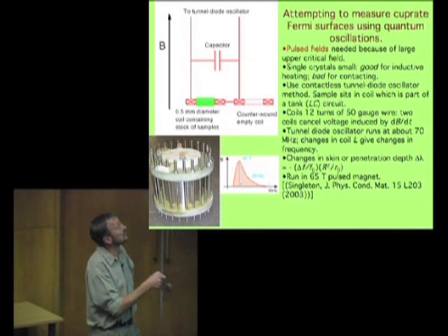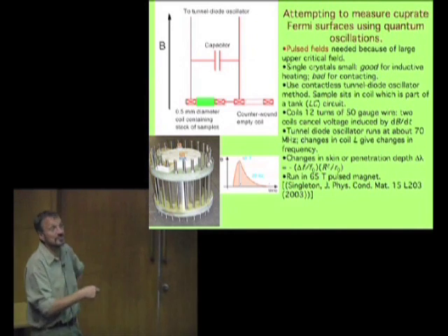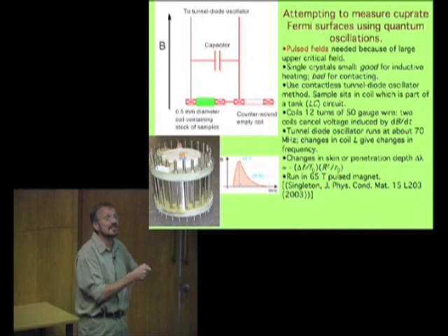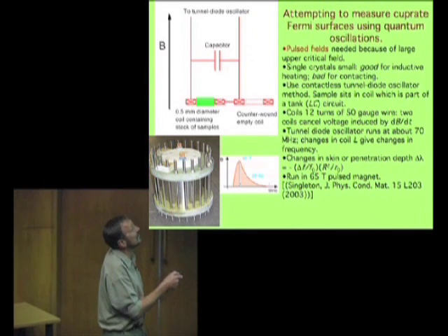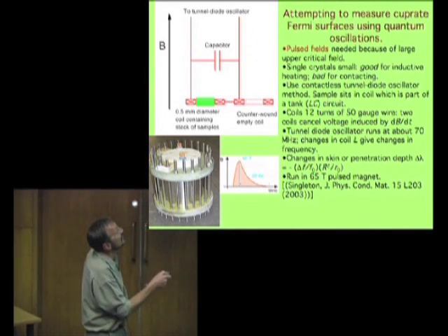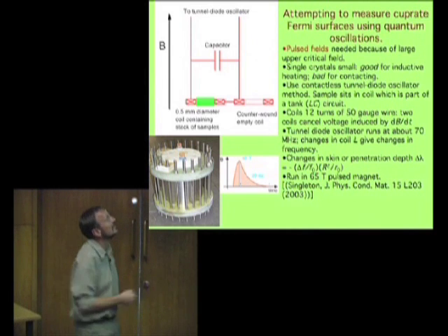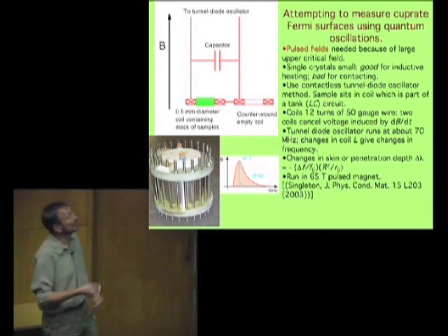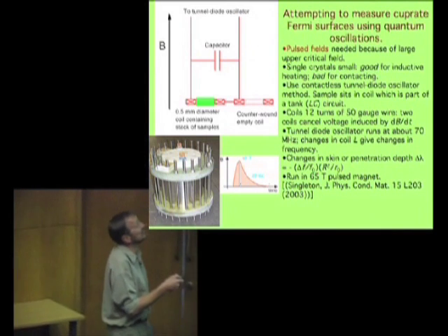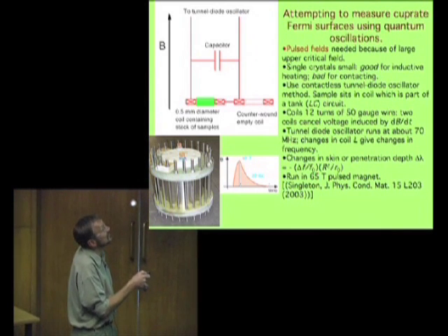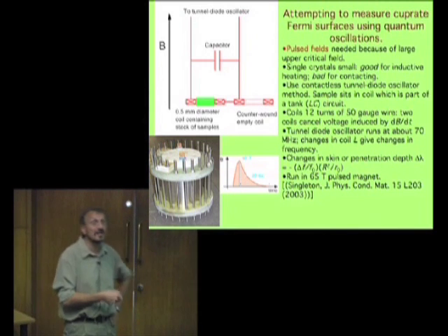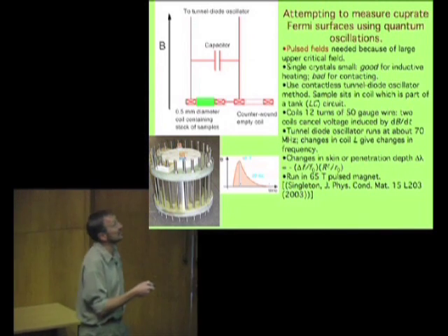Now, if the sample's conductivity changes due to oscillations or anything like that, its skin depth will also change. That means that the penetration of the oscillating magnetic field in this little coil here will lessen or grow depending on what happens to the penetration depth. This will change the inductance of the coil, so the frequency at which this thing resonates will also change.